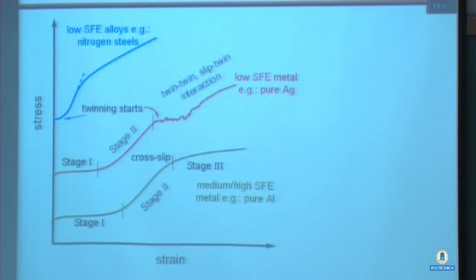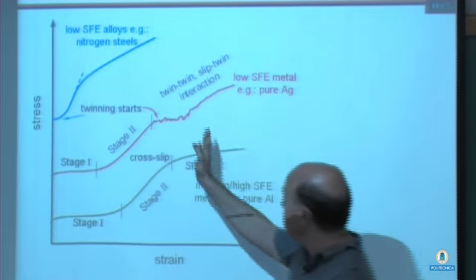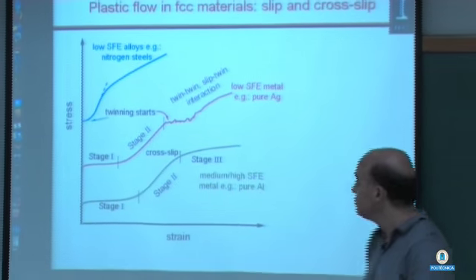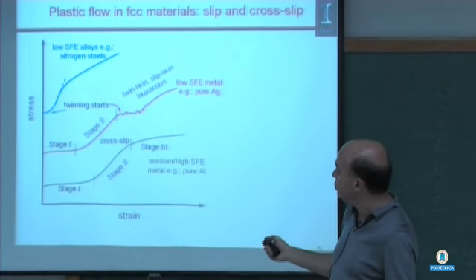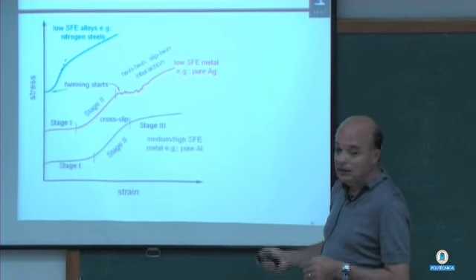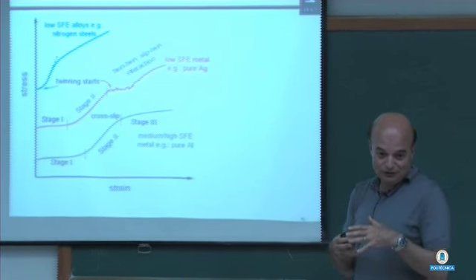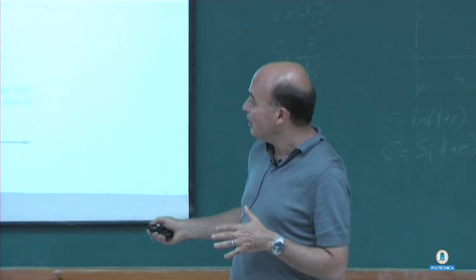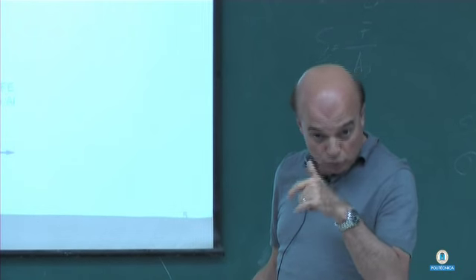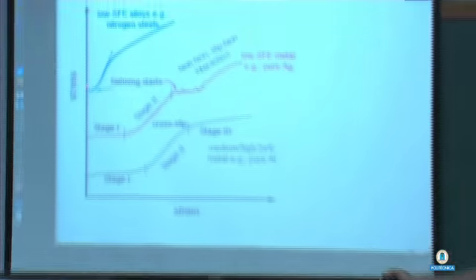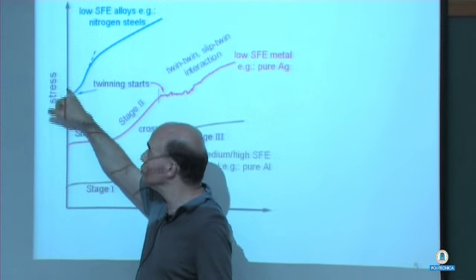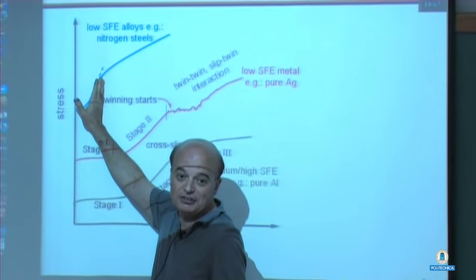Hadfield steel, one of those steels that I work with, actually shows upward curvature. The stress strain curve is like this because of the slip twin interactions. Now, these are all pure metals. In alloys, they are already strengthened, so they don't start at a low yield stress, they start at a higher stress. So you will initiate twinning right from the beginning, and this is the upward curvature that I was talking about. There's twin slip interaction going on here, and this is a very desirable property.